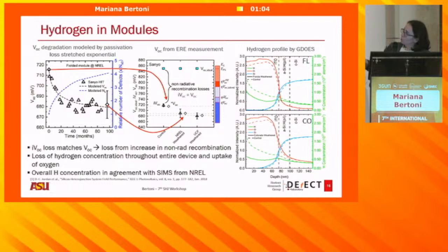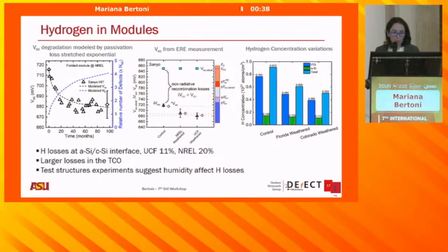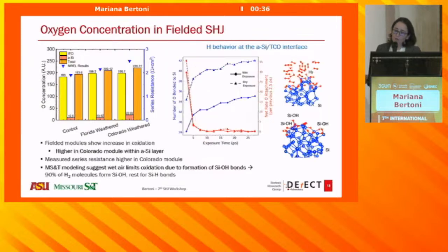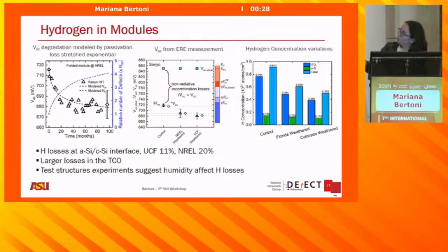The other thing that we also see is that when we do glow discharge optical emission spectroscopy for modules that have been fielded in Florida or in Colorado, we see a gigantic drop in hydrogen in the TCO, which is something kind of strange. And then also in the amorphous silicon interface that we saw in the stacks. Finally, the other thing that we see is a change in the oxygen concentration. So let me just move on, because I don't have a whole lot of time. I think the important thing to note in here is that, did I press too much? Okay, so you have a hydrogen concentration variation.